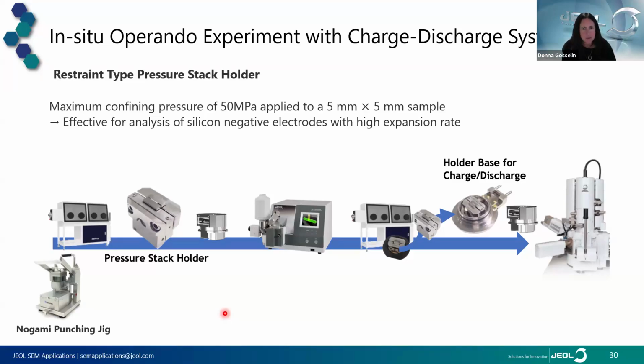In this experiment, we're using NMC as a positive electrode and argyrodite type sulfide electrolyte. And there were a couple of different negative electrodes that are available, one with a silicon composite, the other with a silicon coating.